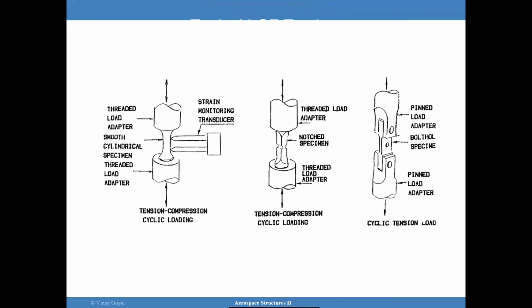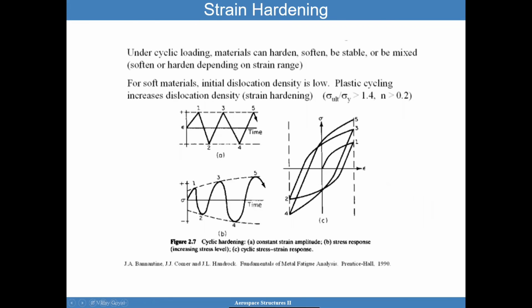Here's some of the apparatus really used in gathering some of this data. You have it for tension compression with a notch and then with a hole. And the strain hardening behavior is also found, and that becomes important when you're doing these calculations. Under cyclic loading, materials can actually harden, soften, or be stable, or be mixed. For soft materials, the initial dislocation density is low. The plastic cyclic behavior increases the dislocation intensity or density.